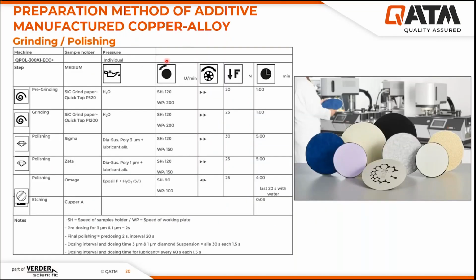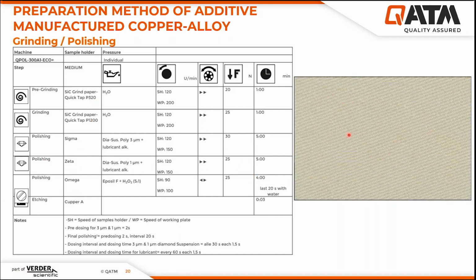Quickly, I introduce you the preparation method of copper alloys, the additive manufactured copper alloys. Here are the parameters. Once again, we use the SiC paper P320, P1200 for the grinding, and then Sigma for 3 micron and Zeta for 1 micron, and shortly for 4 minutes final polishing. Here you can see the structure of the Sigma polishing cloth, it is a wool polishing cloth, and you can use it for 3 micron.